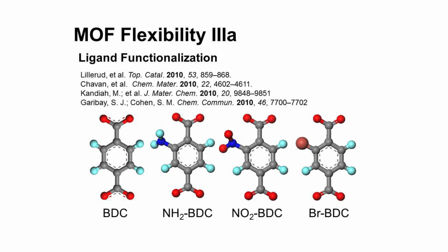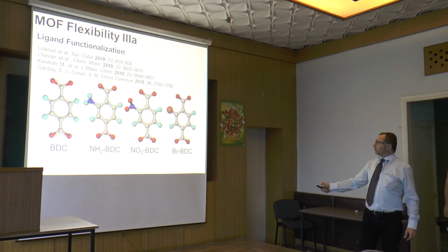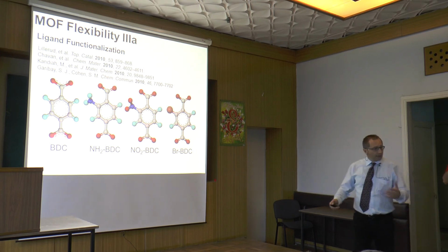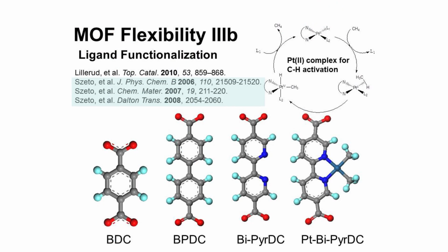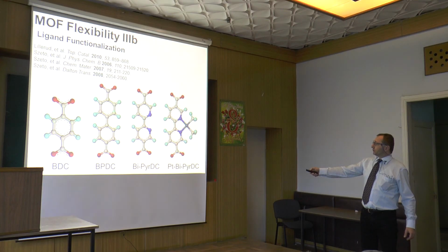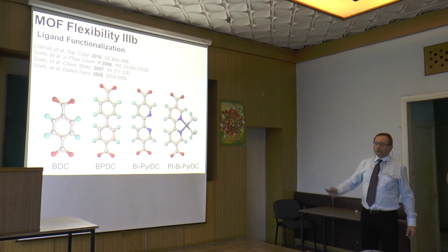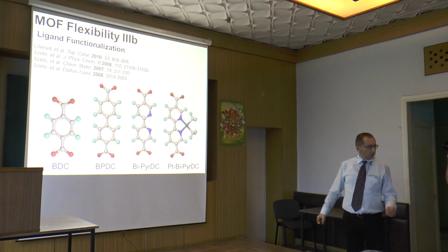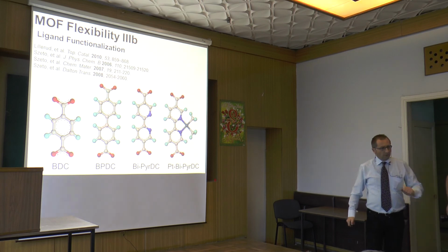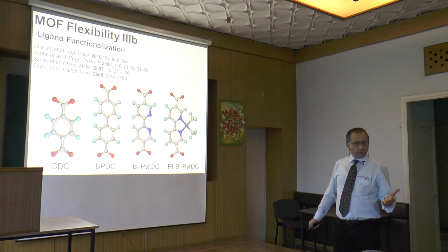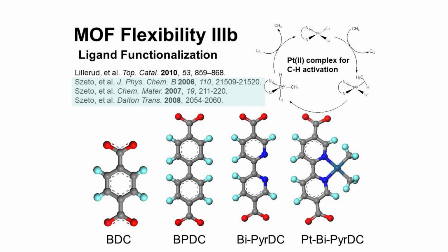And then we can play with functionalization. So we can put here, this is the standard linker, we can put NH2, we can put NO2, we can put bromine. For instance, we're using this linker, this is the longer linker. If we substitute this carbon atom with 2 nitrogen, then we can link a platinum-2 square planar complex, or an iridium-2 square planar complex, or the copper-2 or the nickel-2, and this can make chemistry with this.